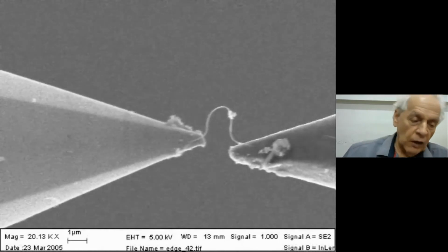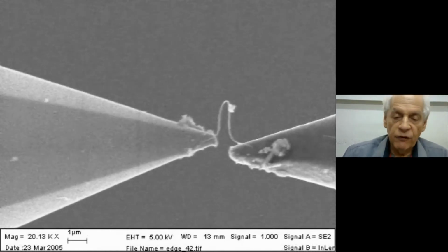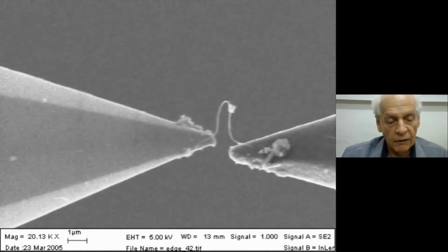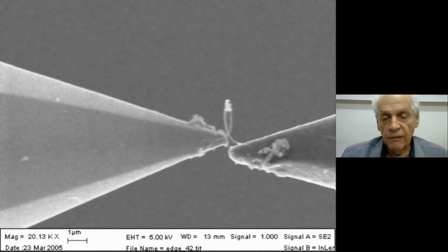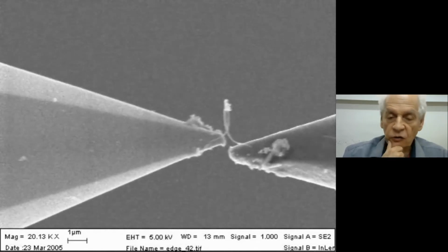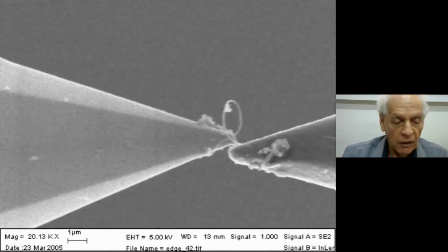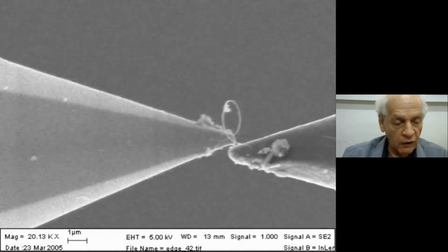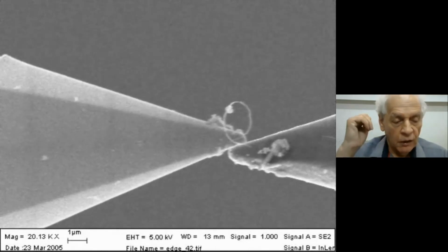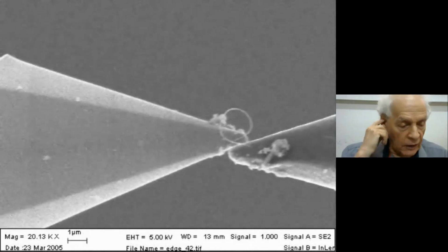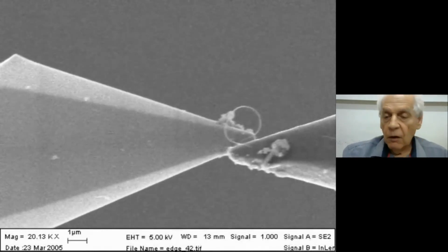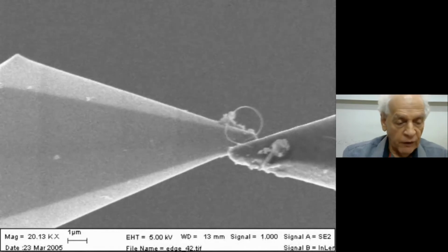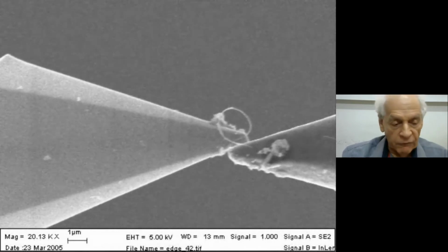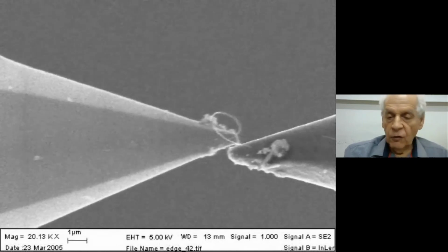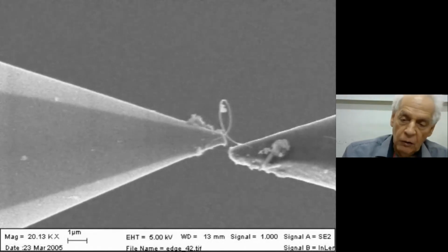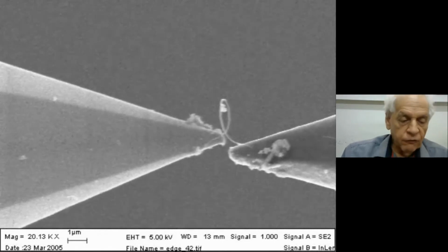And this gives a new dimension to this nanotube. Not only are they strong under tensile stress, but they're extremely flexible. And if you know the mechanics of materials, usually you see materials which are very strong and robust, like ceramic, but with very low fracture toughness. If you bump into it, if you give it a hit, it will break. On the other hand, you have materials like rubber or plastic, which are very foldable, very flexible, but they are very weak, they are not strong. So here you have a material, the nanotube, which is both strong and flexible.